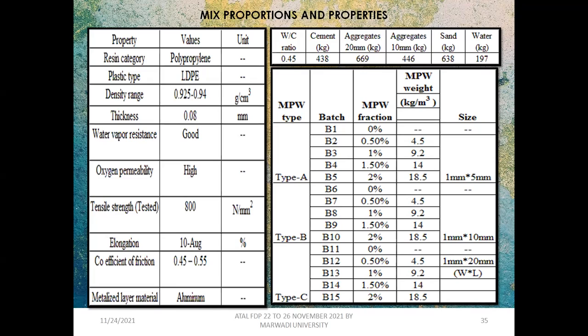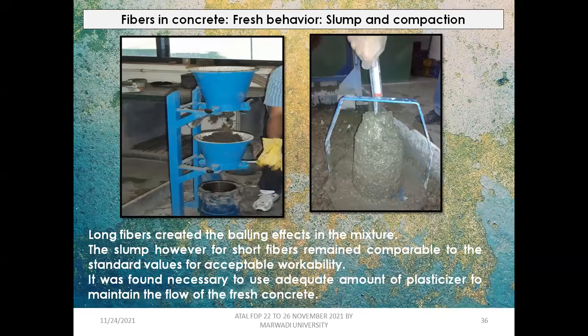Also, we varied the proportions or fractions of the plastic fibers in the concrete. You can see the weight also: if you add typical metallized plastic fiber up to 2%, it weighs roughly 18 to 19 kg per cubic meter, for 5 mm fibers. So you can say that 5 to 10 or 20 mm length, we found workable or acceptable when converting into fibers or flakes.